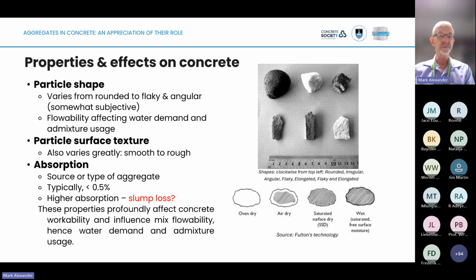The particle surface texture varies greatly from smooth to rough. I'll give you some pictures just now. And then lastly, absorption, of course. In South Africa, because we use largely hard crushed rock of fairly unweathered sources, usually our absorptions are less than 0.5%. In other parts of the world, that's often not the case. And if you start using a material like a recycled aggregate, you'll be up around 5 to 8%. So you really have a very different situation altogether. And certainly some of the Lesotho aggregates can have absorptions up to 3 or 4%. And that needs to be accounted for. It can have very significant effects on slump and particularly slump loss. So this really is an important parameter.